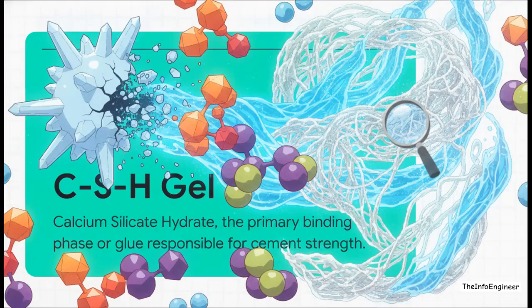As that protective ettringite barrier slowly breaks down, our main silicates, the C3S and C2S, really start to react with the water, and they create something called CSH gel, or calcium silicate hydrate. This gel is absolutely the hero of our story. It is the fundamental molecular glue that turns a fluid, plastic slurry into a dense, impenetrable artificial rock.